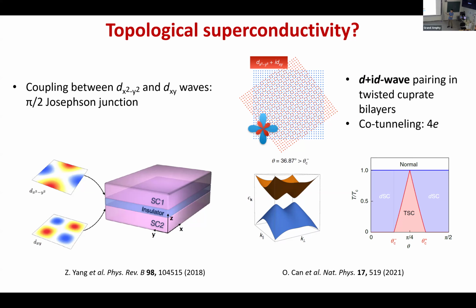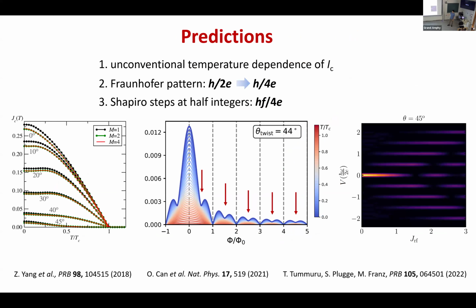So this is actually topological, because it's chiral, d+id and d−id, and it also opens a gap in the spectroscopy. D-wave actually has a linear dispersion, so the gap is not opening in all of momentum space. But now, because of this pairing, you open the full gap in your dispersion. And people predict that around 45 degrees, you can have this topological superconductivity. So if this is proven, this can be a system with very high temperature, 90 Kelvin. Maybe not exactly 90 Kelvin, but if you go a little lower, maybe 80 Kelvin, you can have topological superconductivity. And also it's 2D because you just need 2 layers. So there are some predictions for this.